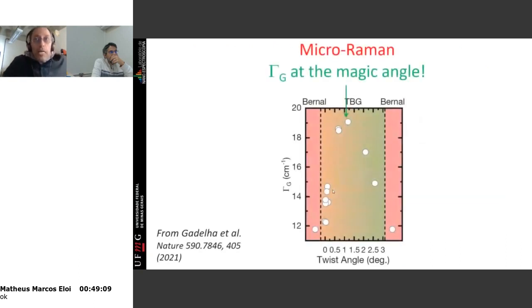And to finish, we measured the phonon lifetime by changing the twist angle between 0 and 3 degrees, and we demonstrated that the phonon line width is maximum at the magic angle. So this is the situation where you have the best electron-phonon coupling all over the material, and this is also where you have superconductivity, although the superconductivity in graphene is not necessarily related to phonons, and this is still under study.